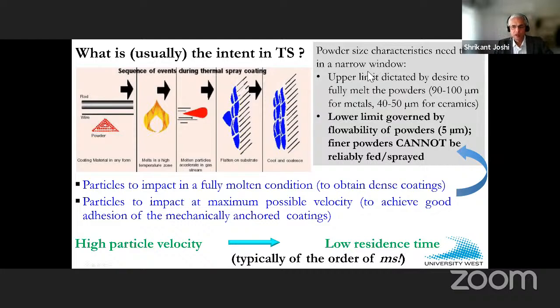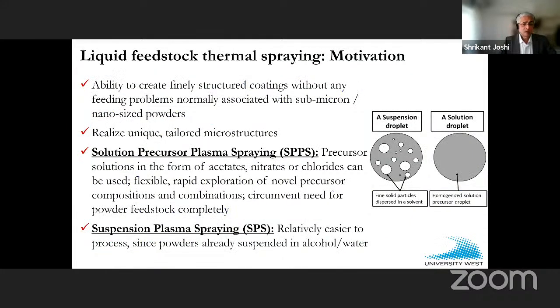But then there is also a lower limit, which is often dictated by the flowability of the powders. Typically, if your powders are 5 microns or lower in size, it's difficult to reliably feed them, and therefore also to reliably coat them. And that really takes us directly to the motivation for employing liquid feedstock. This is the most convenient avenue to create finely structured coatings without encountering the feeding problems that are normally associated with use of few micron, submicron, or nano-sized powders, and thereby realize some very unique microstructures.